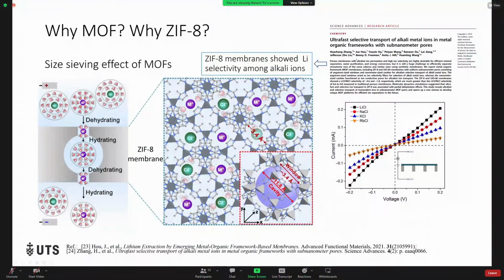According to a simulation study published in Science Advances, some MOFs with sub-nano channels, such as ZIF8, have the property of ion selectivity due to the size-sieving effect. Specifically, the lithium and the competing cations become dehydrated when entering the ZIF8 framework, and then rehydrated when they exit, because the hydrated ionic diameters of these cations are larger than the window diameters of ZIF8, but the dehydrated ion diameters are smaller than it.